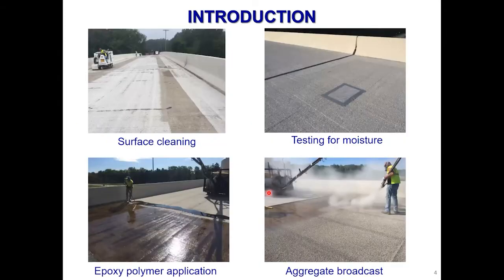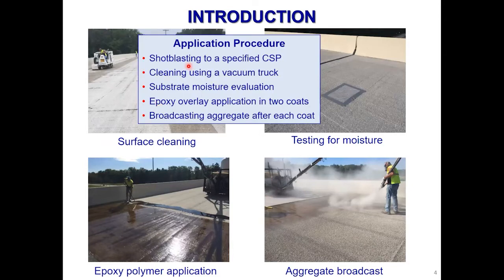So typical application procedures involve surface cleaning, shot blasting, and surface cleaning. Then we need to check the moisture evaporation in order to understand if the rate of moisture evaporation is acceptable. And then we apply the overlay in 2 coats. Within each coat, we apply aggregate, or we broadcast aggregate.